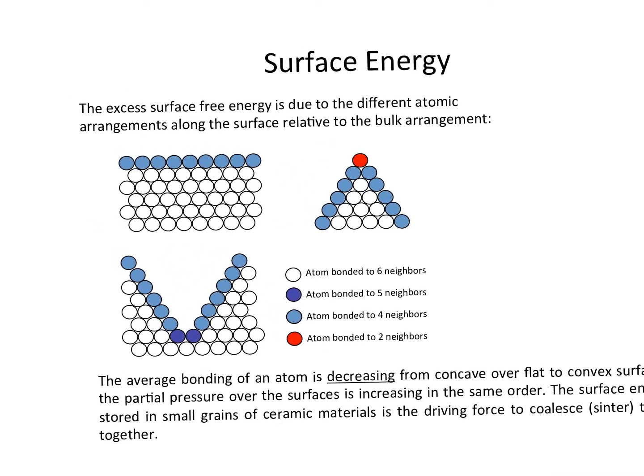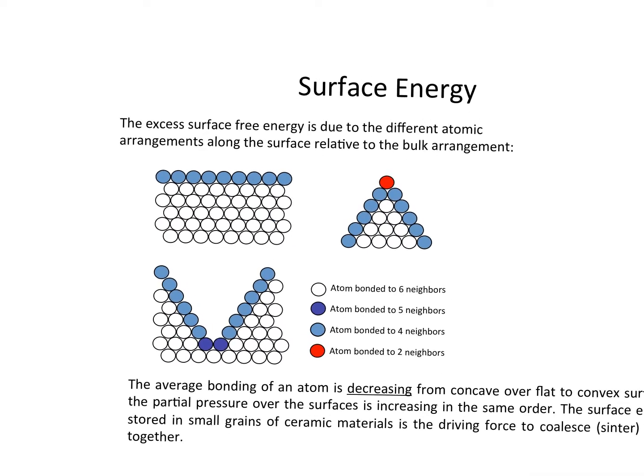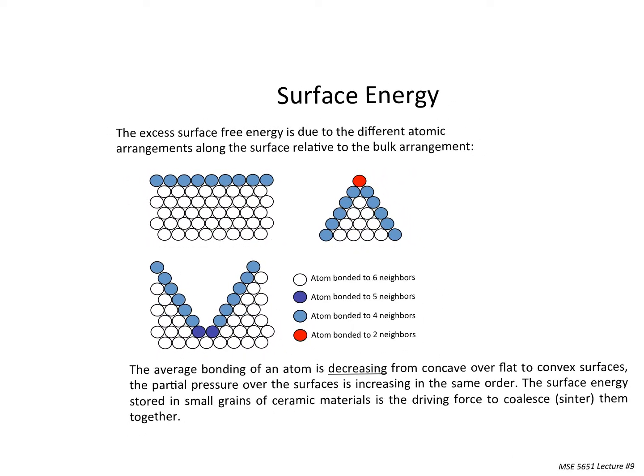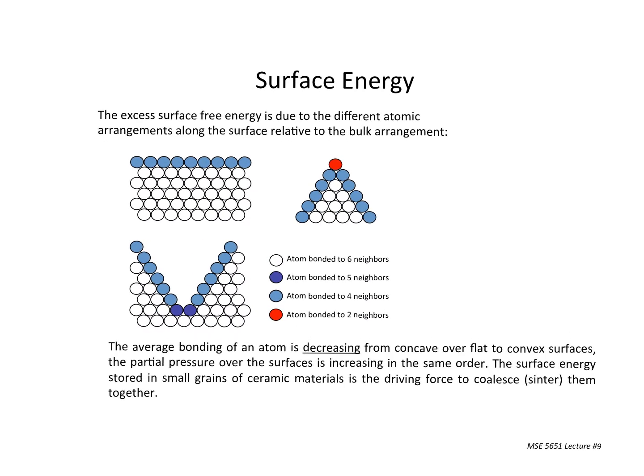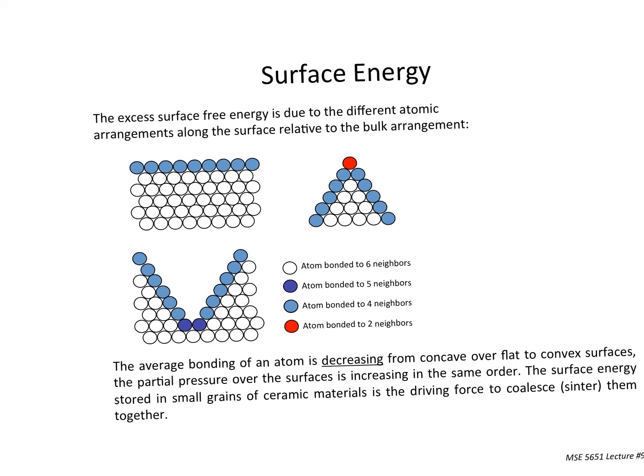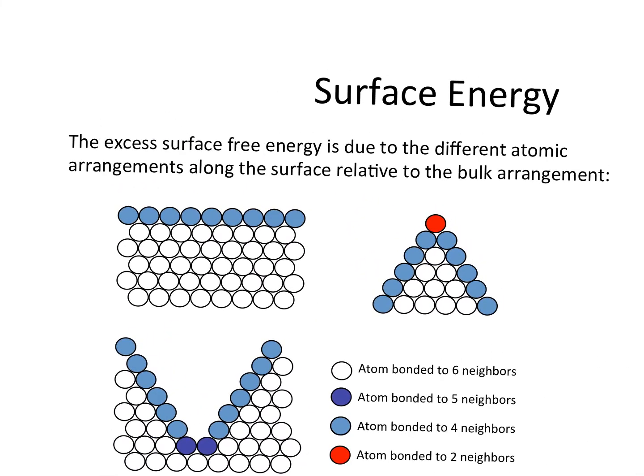We want to talk about surface energy, and this relates to what atoms will tend to do when they're placed in these configurations. These represent configurations that exist when we have a bunch of typically very small particles in the system. You should all know that when we have a surface, that surface always consists of atoms, and those atoms there at that surface in this nice flat configuration are going to be unhappy because they are experiencing a bunch of unsatisfied bonds. That's what makes water absorb onto them and anything else that's in the environment. These guys are higher energy, and the system as a whole would like to get rid of them. That's what drives everything we're talking about today. It's trying to get rid of atoms that are at a higher energy state, and this is how we look at this as an overall system trying to minimize its energy.